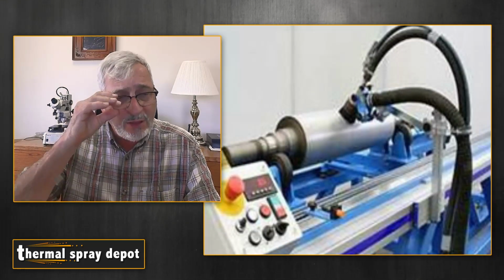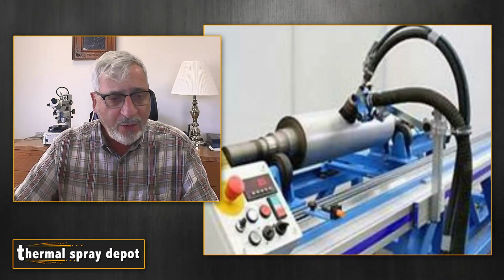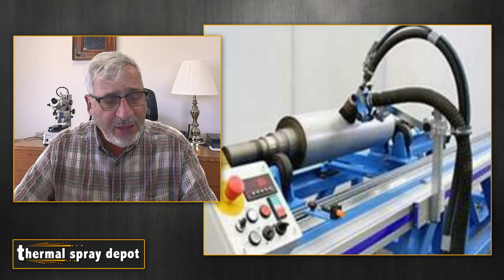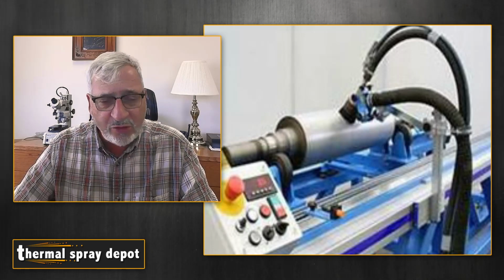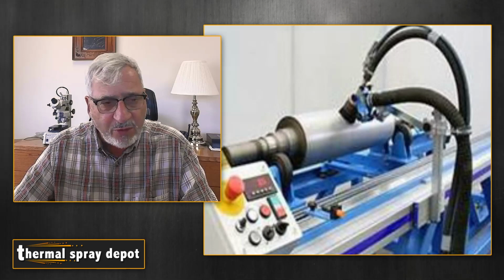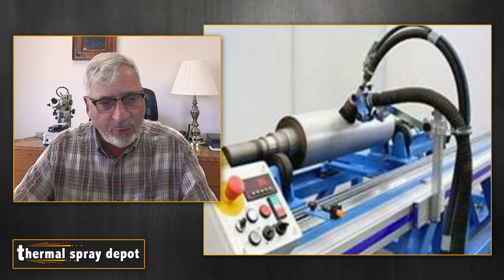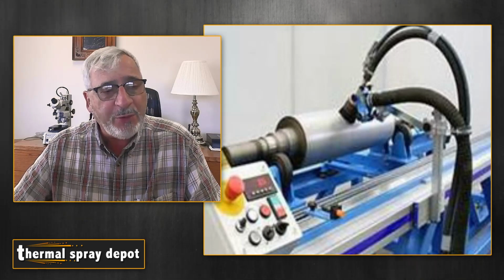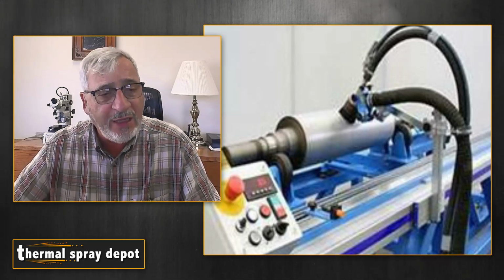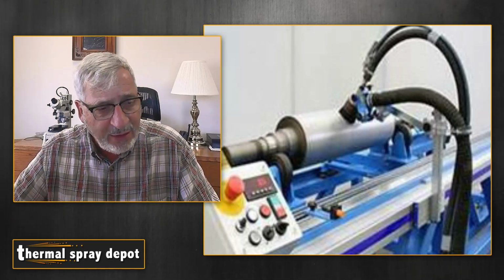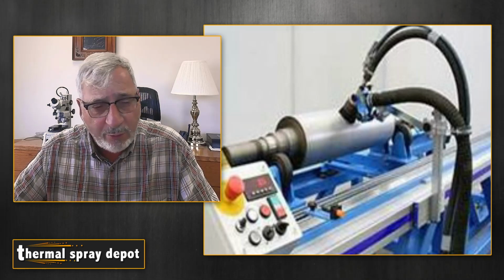Now, a lot of people say, well, we don't want to use grit blast because it makes a mess in our machines. This is something called a vacuum blast. What we have here is the grit blast. We're grit blasting the surface of that roll, and at the same time, there's a vacuum sucking the grit back out. On this particular device, this whole thing is a grit blast device, and the only thing this machine is used for is rotating the roll while they're blasting.